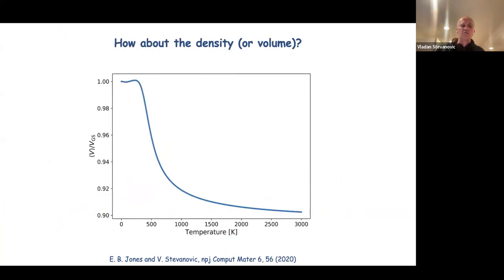Another quantity that is usually discussed is the density or the volume. What you see here is just the average volume as a function of the temperature used in averaging, and how it depends on temperature. So at low temperatures, of course, you get the volume of the ground state diamond silicon. This is the ratio of average volume relative to the ground state volume, and you get a crystalline phase at low temperatures. And then as the temperature increases, the volume goes down, meaning the mixed state is denser than the crystalline phase.